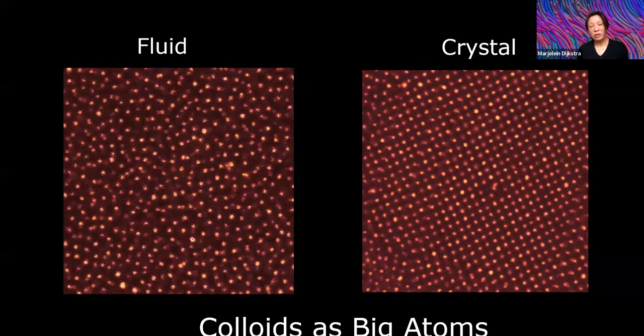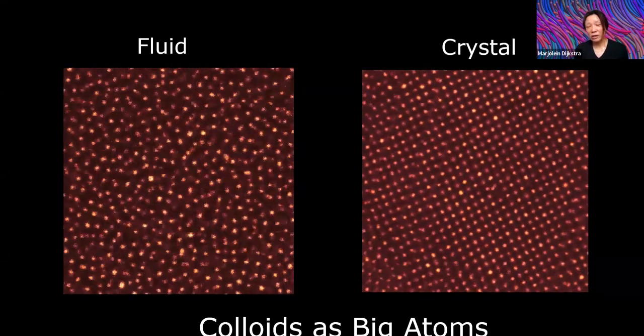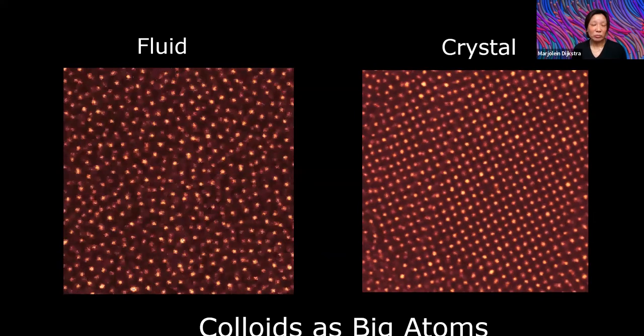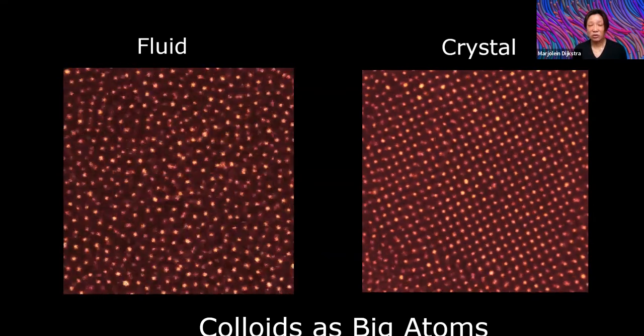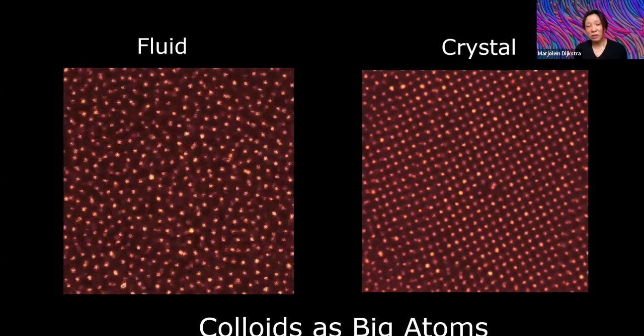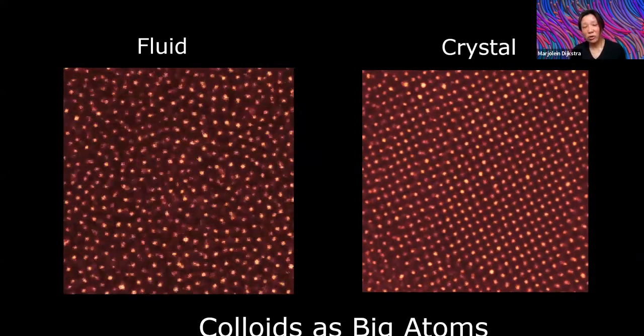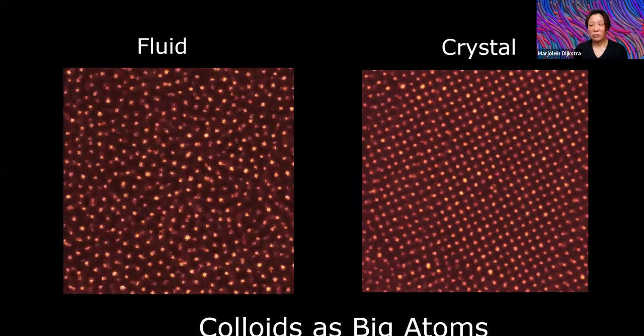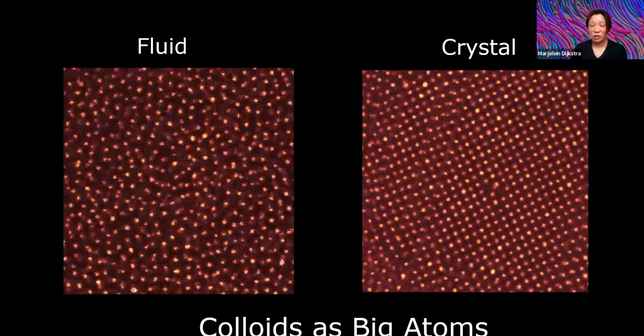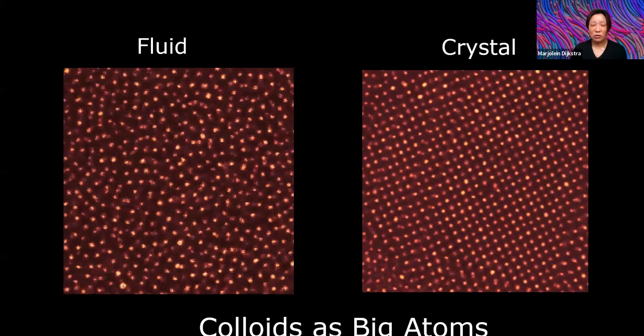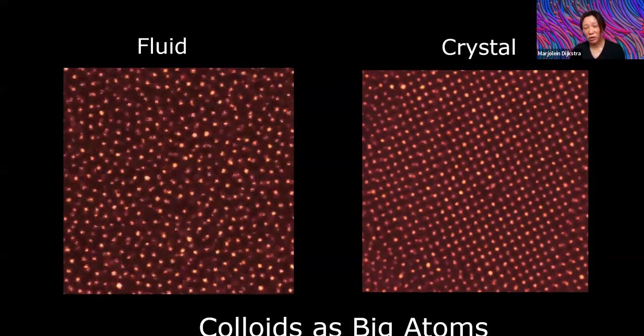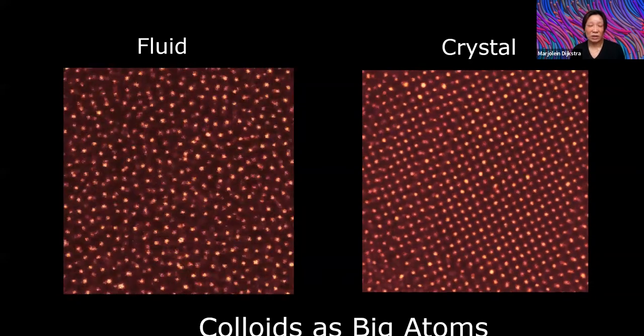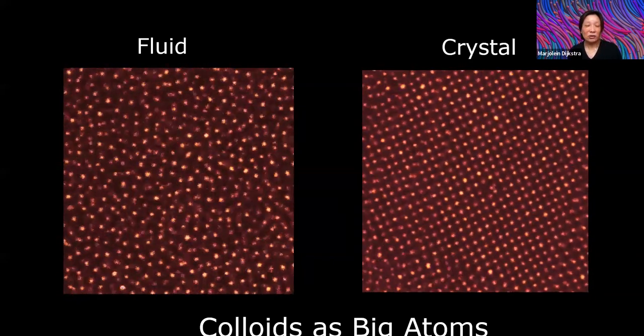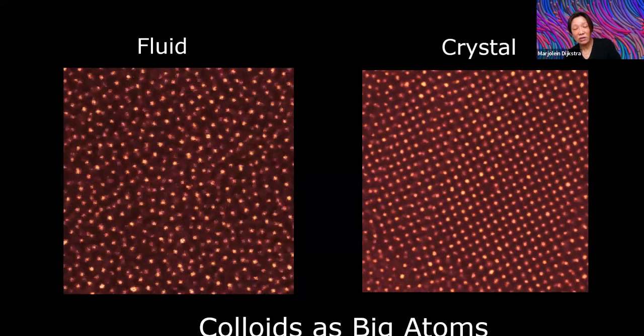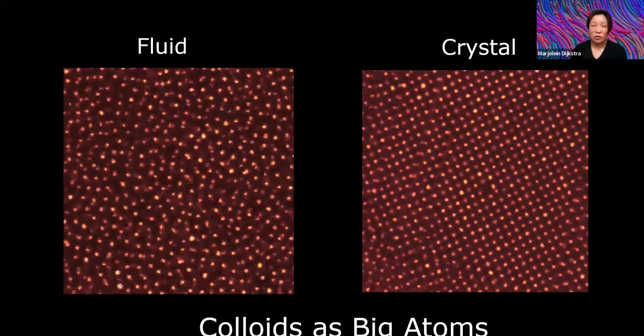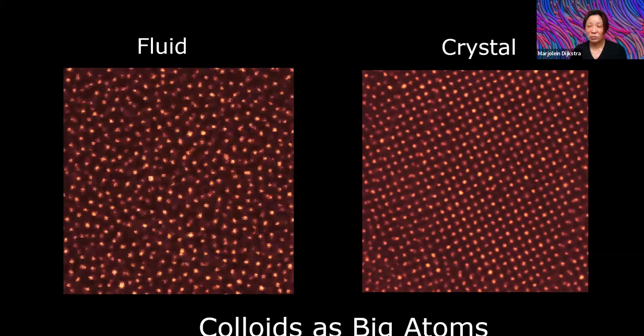And here's an example. These are a few hundred nanometer silica particles that are dispersed in a solvent. One can clearly see using these confocal microscope images that the particles are moving. There's eternal motion of all these particles, this jittery motion that goes on forever. And you can see that if the density of these colloidal particles is extremely low, they just move around in random directions.